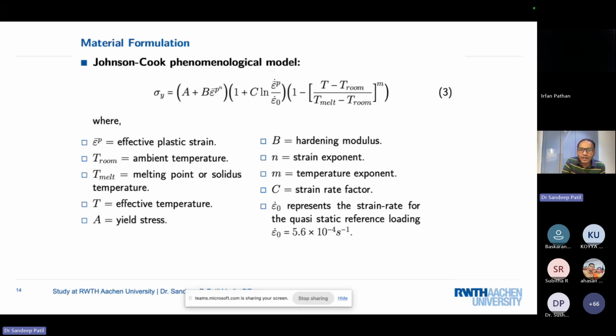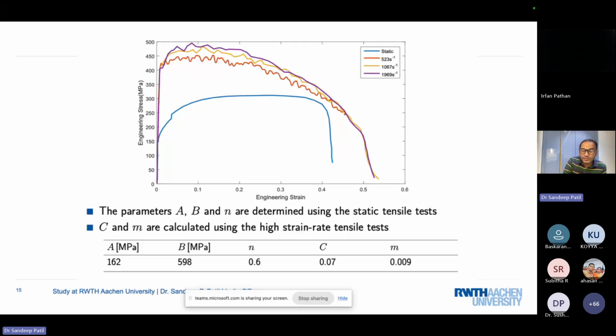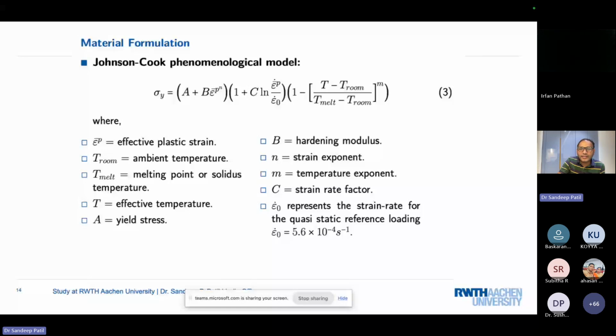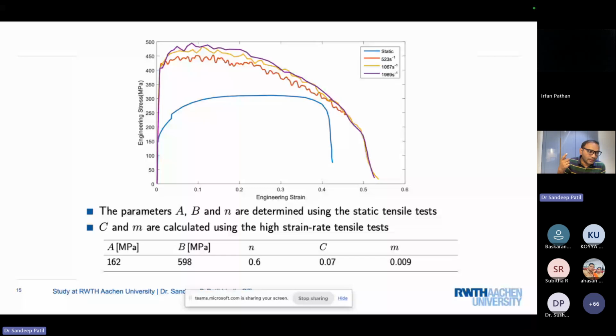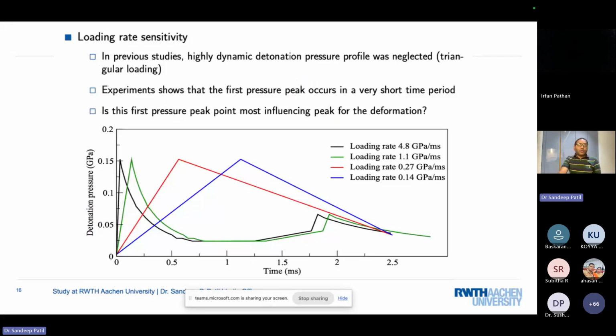These are the parameters determined using the static tensile strain test, so they are not rate dependent, but the other parameters, like C and m, are different. If you look at the strain rate factor and the temperature exponent, if temperature plays a role in it, then it is calculated using the high strain rate tensile strength. That means some of the parameters are calculated with the static strain, and some are calculated with the high strain rate. So what was the gap in the research?